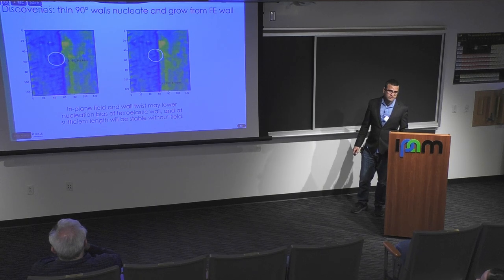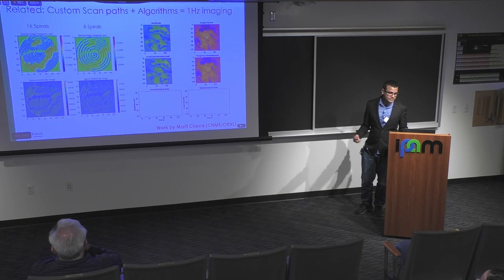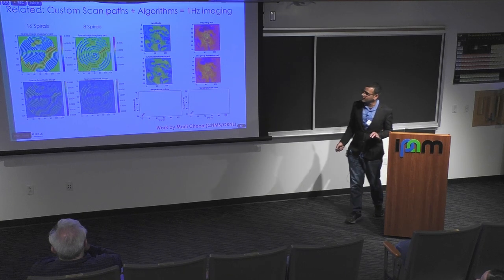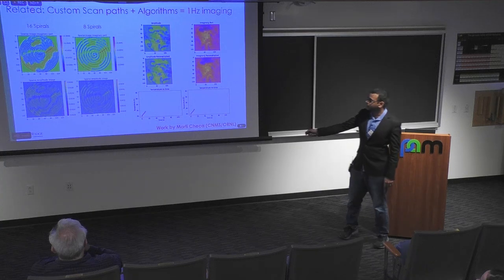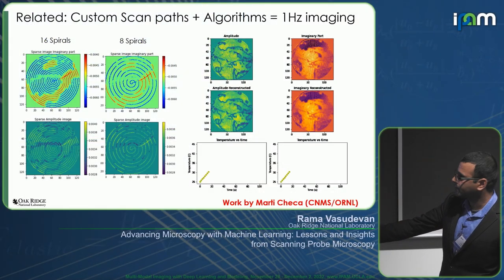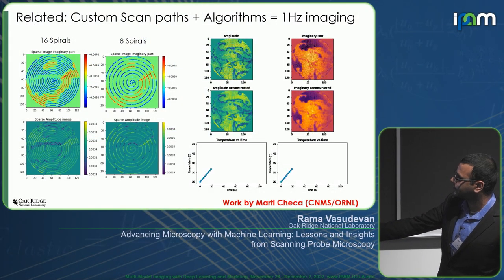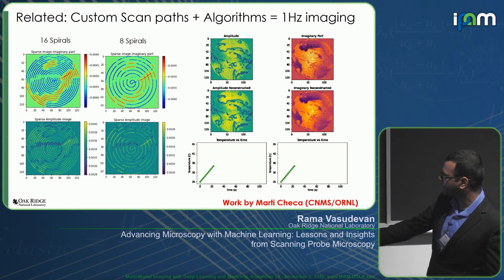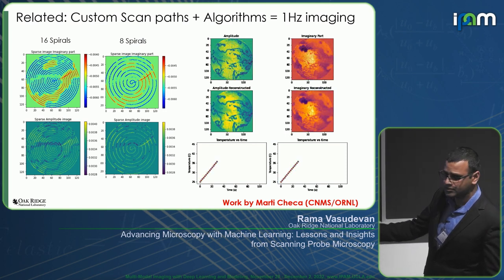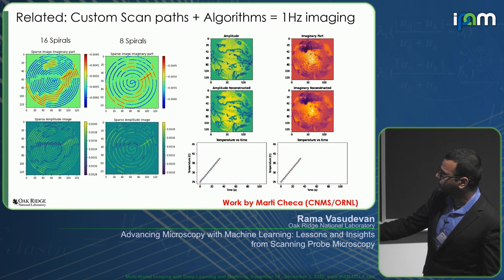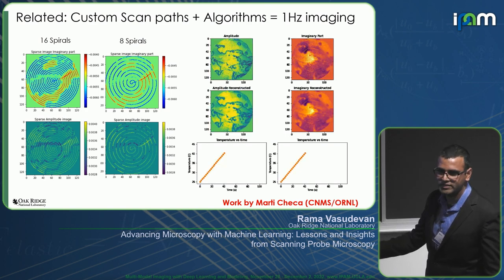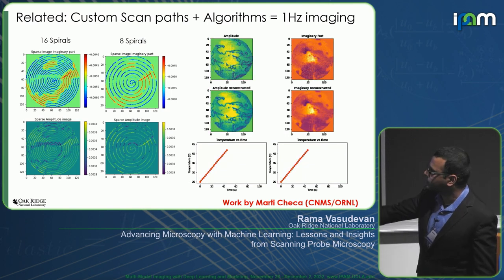But we need to get faster, right? Each image here takes 4 minutes, and that's too slow. How can we get faster? We can get faster through spiral scans and compressive sensing. And so here is a spiral scan that we collect. This is work by Marti Checa that he's currently doing. We still need to optimize this. But basically what we can do is instead of taking 4 minutes for a scan, we can take scans every second with this method.